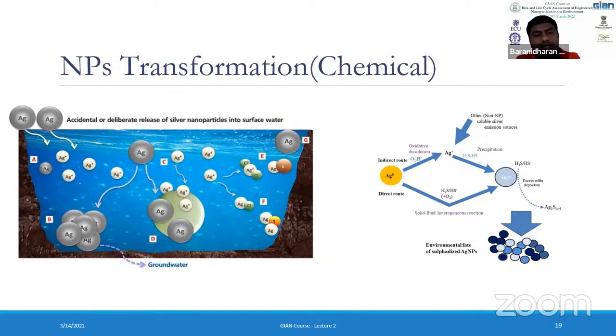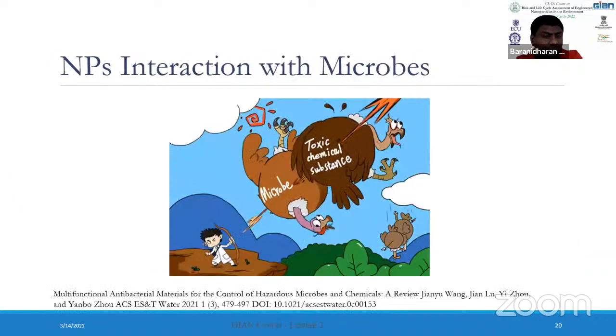But when silver reacts in a system that is not well aerated, such as sewer, where sulfide is present, silver forms silver sulfide in the wastewater. So this also plays a vital role with respect to the surface chemistry, the chemical composition, the morphology, the naturally occurring organic matter, the surface composition, and the reactivity in the dissipation of these into the environment.